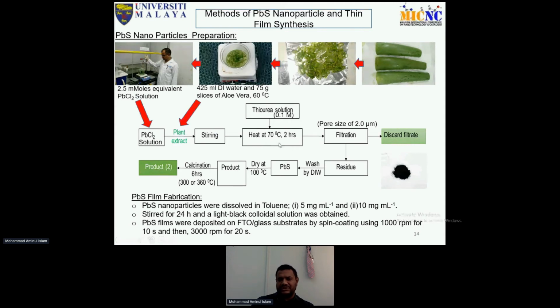Stir for 2 hours. Then we filter it with a pore size of 2.0 micrometer, and from the filtration we collect the residue. The other things we discard. This residue is washed with DI water, and this residue is basically the lead sulfide. It is a gel-type substance. Then we dry it, and then calcination at two different temperatures for 6 hours. And this is our final product. You can see the pictures.